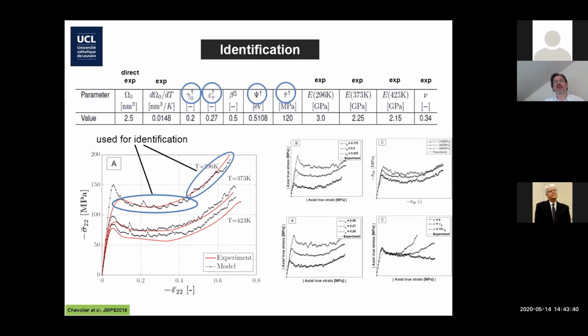All right, so we have been using the test at room temperature to adjust the 4 fitting parameters which are here. For the pressure dependency, we need one more test. These are compression tests, by the way. We need a tensile test or a shear test to adjust the beta parameters. But we use one curve to capture the rehardening, the softening, and the right plateau value here, in order to adjust these 4 parameters. And the 2 curves below are different tests done for different parameters, just to show that we did the parametric study. And these are the predictions that you get for the 2 other temperatures by keeping the parameters constant.